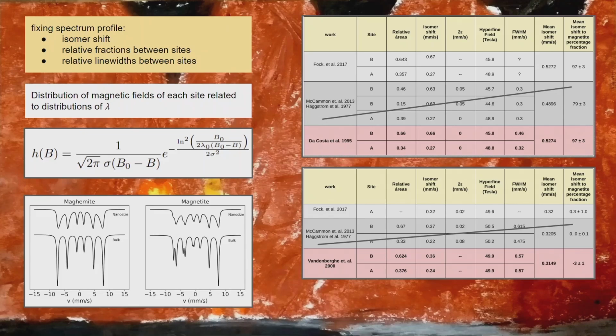If we have a distribution of sizes, we will have a distribution of hyperfine field, and we can then calculate which will be the nanomagnetite or nanomaghemite spectra that are here. This is a proposal of how the bulk spectra is affected because of the size. So to do that, we need a bulk spectra. I am working with nano spectra, or nanoparticles.